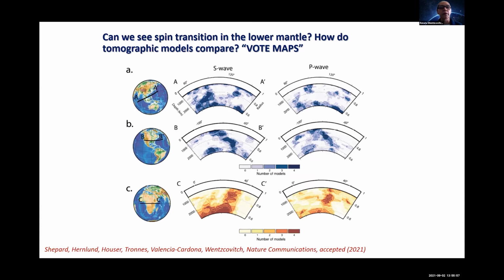They count point-wise in the mantle the number of models that have large heterogeneities, positive or negative. And this is what you're seeing here. These are the cross sections of these mantle regions, and these are our vote maps. The dark regions are regions where 4 models agree that this is a fast region or a slow region in the S models here. Of course, this is not heterogeneity itself, but the heterogeneity is robust. And it's a common feature among all the methods, so then this must be real.